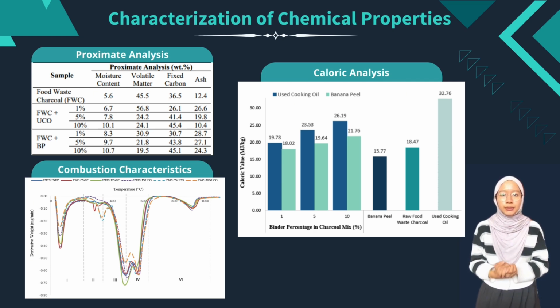Food waste charcoal mixed with used cooking oil samples exhibits a consistent and less pronounced decomposition in the 200 degrees Celsius to 400 degrees Celsius range, indicating a more controlled and stable combustion process with fewer volatiles. This stability suggests that used cooking oil, which acts as a binder in the food waste charcoal briquette, is preferable for applications requiring steady and reliable combustion, making it the better choice for optimized combustion characteristics.